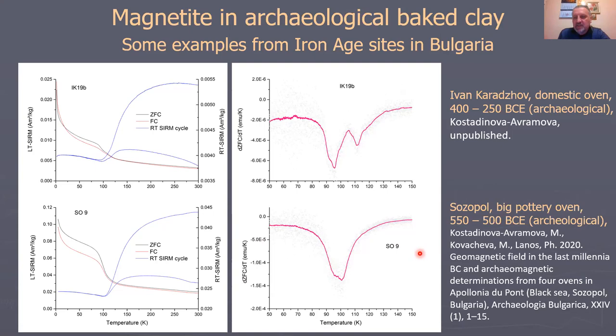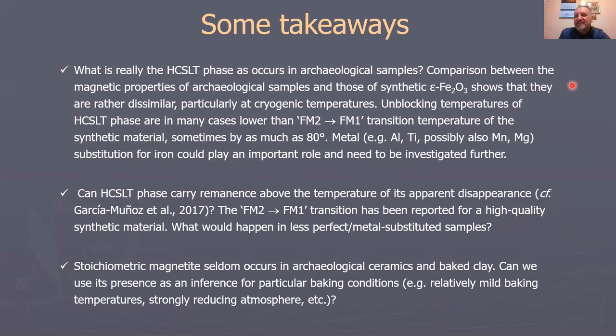And so I would conclude with a few takeaways. The major problem about the magnetic mineralogy of archaeological artifacts is the origin, the identity of the HCSLT phase. And the comparison between the properties of archaeological samples and the properties of synthetic epsilon oxide shows that these properties are quite dissimilar, and particularly at cryogenic temperatures.